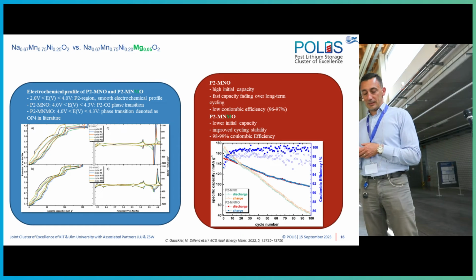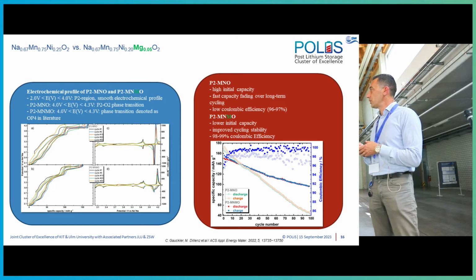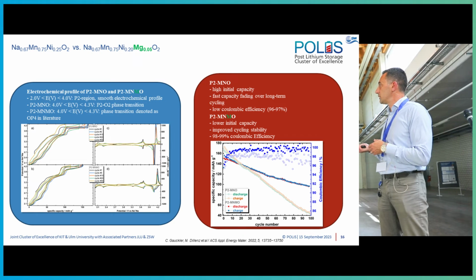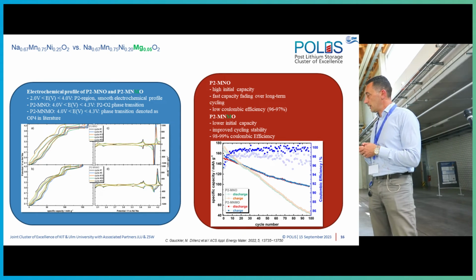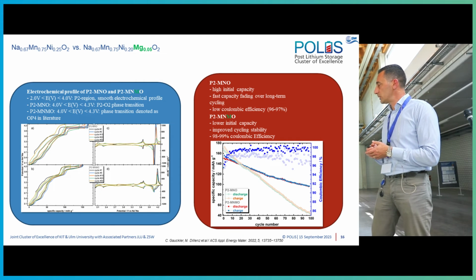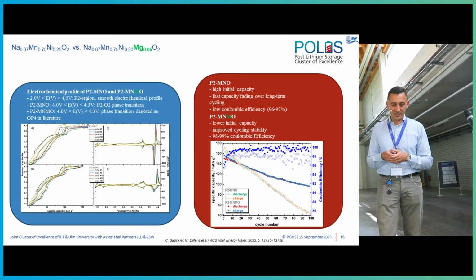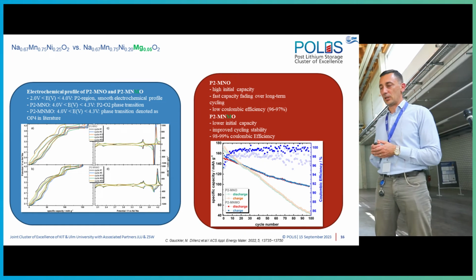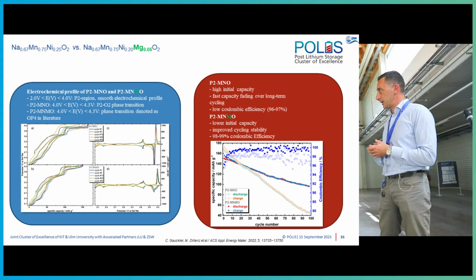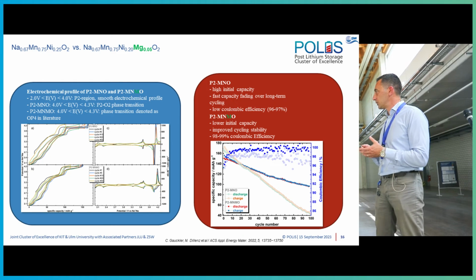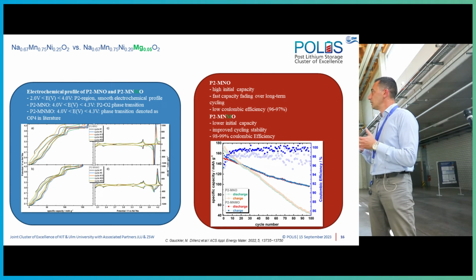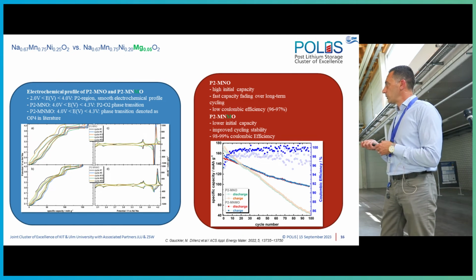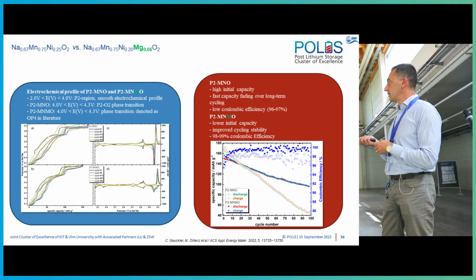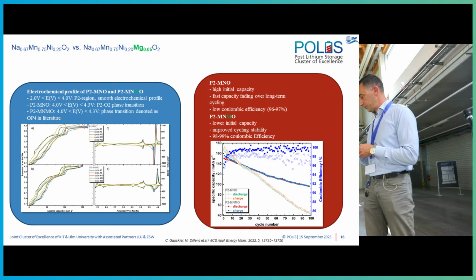Cycling stability, comparing the two, we see that basically the doped material, the magnesium doped material, has improved performance. It's not perfect, as Max said yesterday. Of course, there is still room for improvement of both particle architecture and eventually also the level of doping. But when we see that, what we can say is that the capacity retention is increased and also the coulombic efficiency.